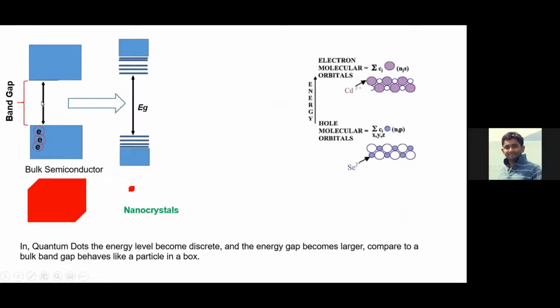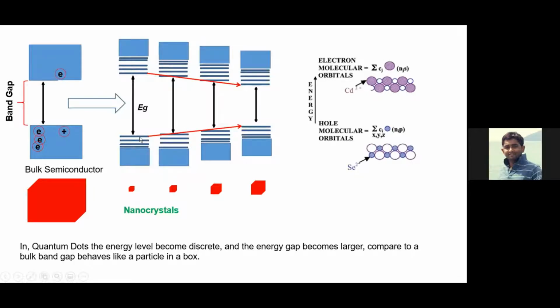As it's a bulk band gap, if it's an emitting material, it can emit a very slight emission, but it's not very good. But when you go to the confinement structure, when you go to the small size, you can see its energy levels are getting discrete, because the overlap between the orbitals is very strong. So you will have separate energy levels, and when an electron goes from the valence band to the conduction band, you have a discrete energy.